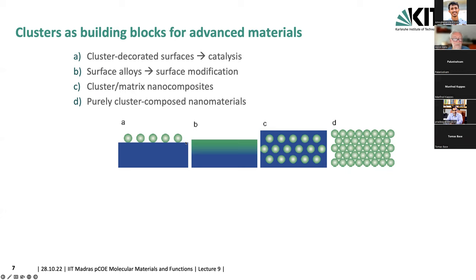This is actually a project which we have in one of our larger scale research projects at KIT on catalysis. What you can also do is, if you increase the impact energy of the clusters onto the substrate, you can make a surface alloy and a surface modification. Of course, it's a bit of a pity to lose the cluster property if you damage it completely and dissolve it in the surface, but you might create some interesting, very metastable surfaces which you could otherwise not prepare.